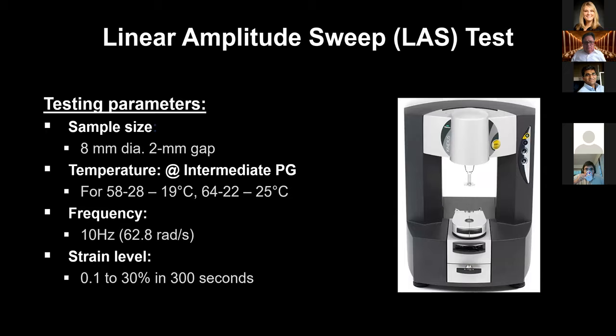Next, I'm going to go through the linear amplitude sweep test. It is a binder performance test that measures fatigue properties of an asphalt binder. LAS uses viscoelastic continuum damage mechanics theory to determine the damage intensity to calculate cycles to failure. This was done at 8 millimeter diameter, 2 millimeter gap. The temperature for the 58-28 was negative 19, 64-22 was done at negative 25, frequency of 10 hertz, and the strain level from 0.1 to 30% in 300 seconds.